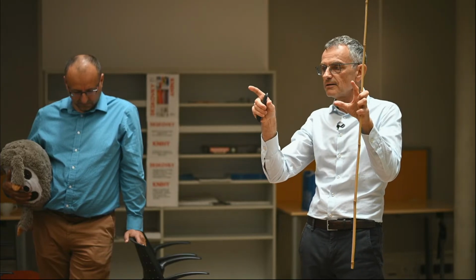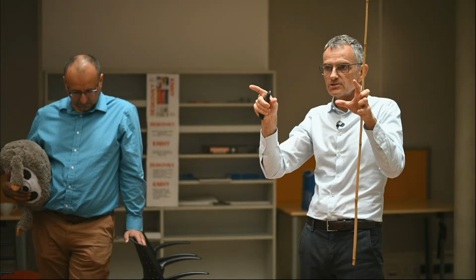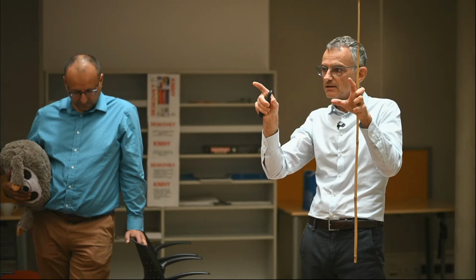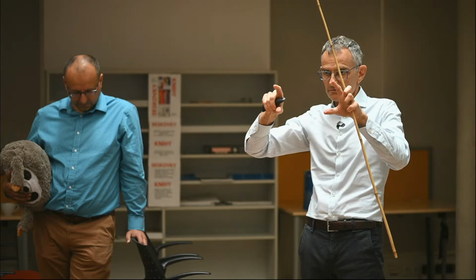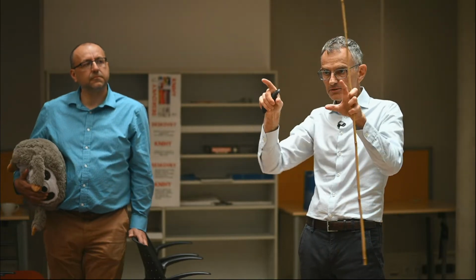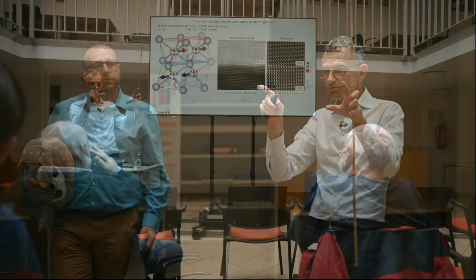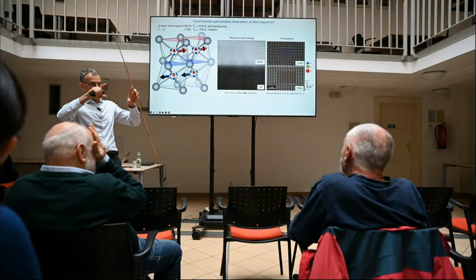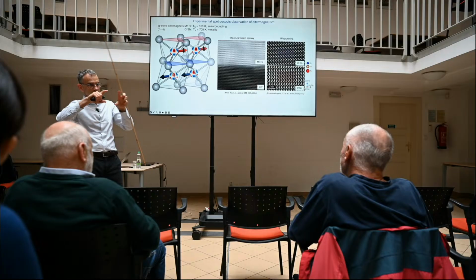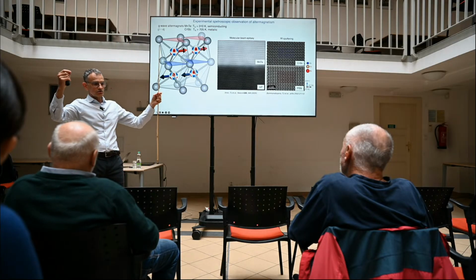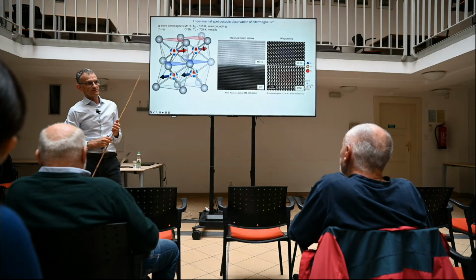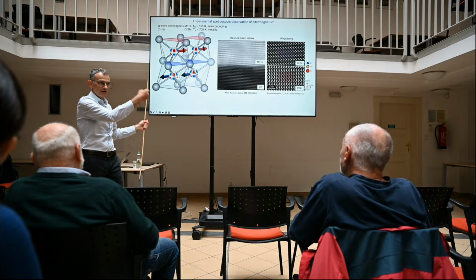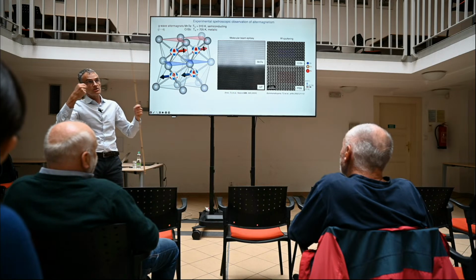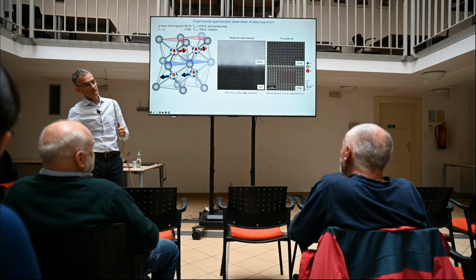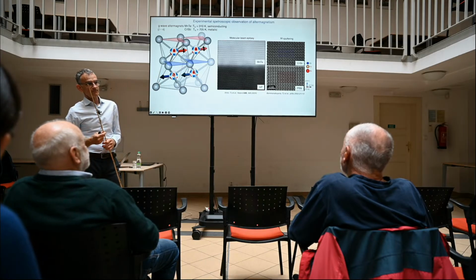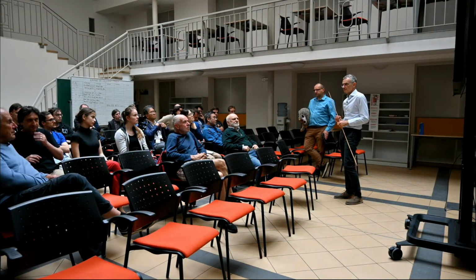But if you, for example by applying strain or something else to the crystal, make these local environments straighten up, so you can manipulate those local environments from mutually rotated to mutually parallel, and therefore introduce a translation symmetry transformation between them, you can turn on and off the spin polarization in the electronic structure. You can turn on and off the altermagnetic phase, or switch it from altermagnetic to the conventional Néel antiferromagnetic phase back and forth. So this is one example.